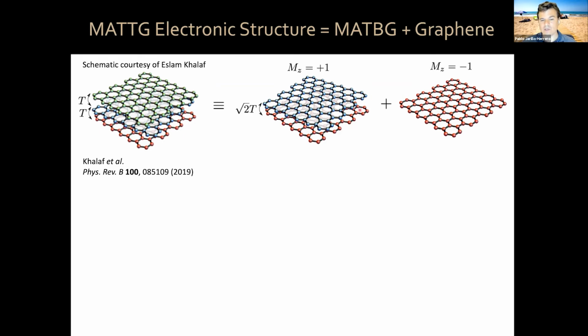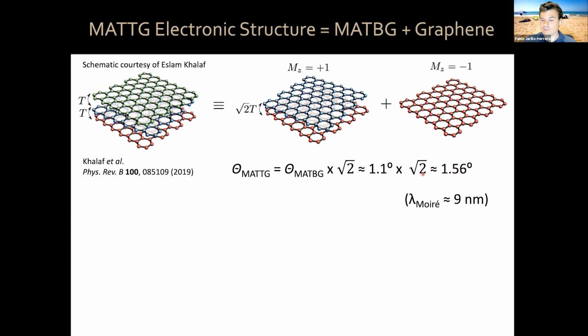This means that, remember that I told you before that the magic angle condition depends on the interlayer tunneling. Because of this square root of 2, the magic angle for magic angle twisted trilayer graphene is that of the bilayer case times square root of 2. So it's 1.1 times square root of 2, so it's 1.56 degrees. Because of this, the angle is a little bit larger, so the Moire wavelength is a little bit shorter: 9 nanometers instead of 13 nanometers. And this system probably has a little bit stronger interactions.